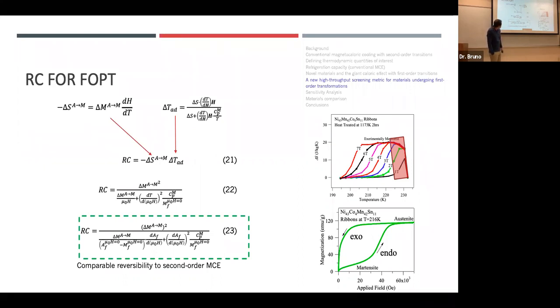Now, okay, still, we're going to get really big refrigeration capacity. With a ferromagnetic material, we can apply 1 Tesla magnetic field and we get some cooling, right? Well, in this material, if we apply 1 Tesla, you can see the whole 1 Tesla line is in that shaded region of the delta S diagram that I said was not useful. Same with 2 Tesla. Well, now, this is a problem, right? We need to account for that thermal hysteresis range, which we kind of did with refrigeration capacity. But I think we need to account for the energy input needed, so coefficient of performance.